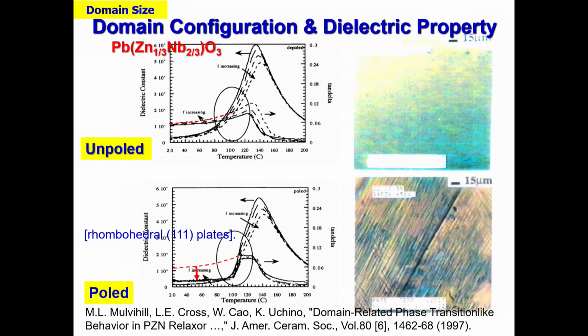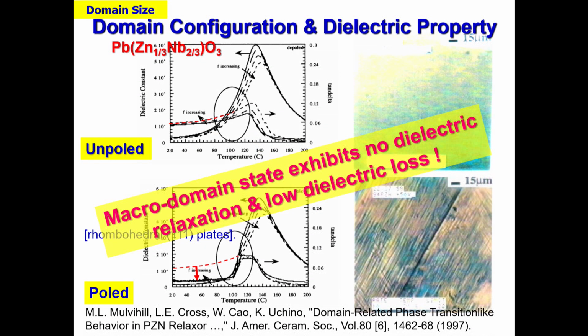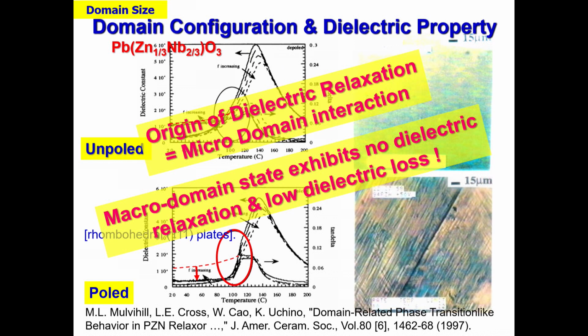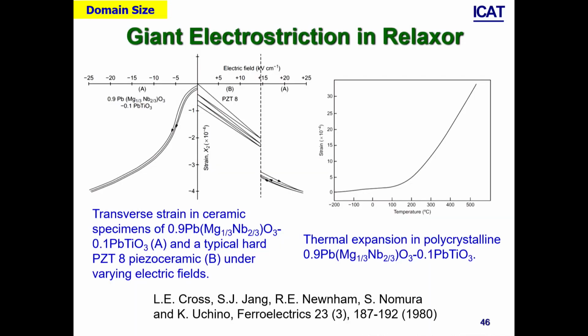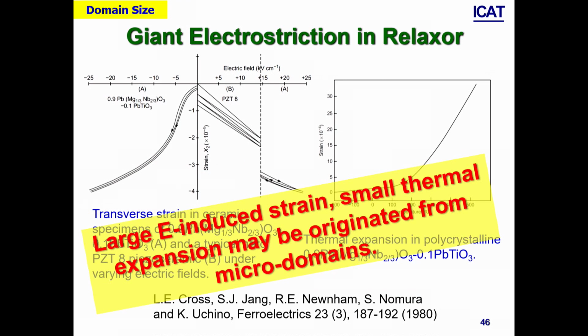And with increasing temperature, this range is like a macro to micro, another phase transition, okay? A domain-related phase transition happened. The macro domain state exhibits low dielectric relaxation and low dielectric loss. This is a very intriguing point. Okay. So the origin of the dielectric relaxation in this case is all microdomain interactions. Okay. And because of lack of time, I will skip the giant electrostriction. So the large electric field induced strain and small thermal expansion may also originate from the microdomains.